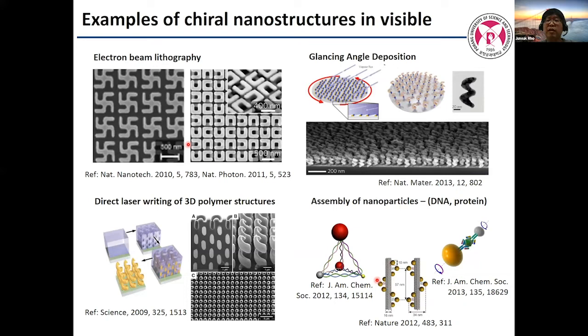And this is using purely a deposition technique, glancing angle deposition from Max Planck. They rotate the stage and can make this zigzag structure by deposition only. And this is direct laser writing from the Karlsruhe group. This is a beautiful technique also. And more recently, chemistry people using DNA origami make this golden nanoparticle chiral template. So this is beautiful. Later I compare with this slide of this center in Nature 2012. It showed the highest chiral property so far, but our chiral metamaterial actually has 10 times larger optical response than this one. So I will show how we do that.